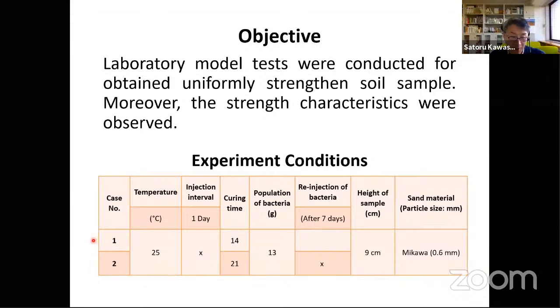Only 2 cases conducted. Case number 1: temperature fixed, both testing cases 25. The injection interval is 1 day. The curing time, number 1, 14 days; case number 2, 3 weeks, 21 days. The initial bacteria amount is the same, 13 grams. Re-injecting bacteria: number 1, no adding, and number 2, added once again 7 days later. The sample height is the same, and the same sand material.